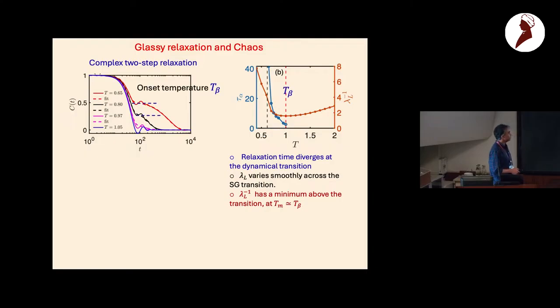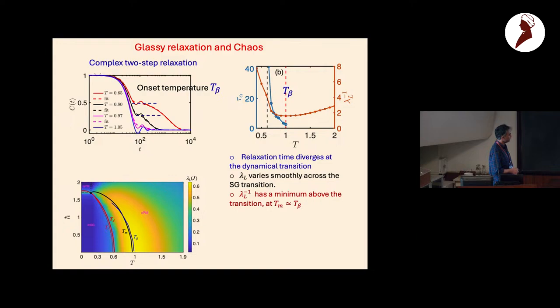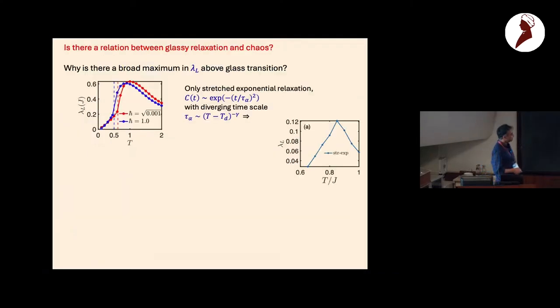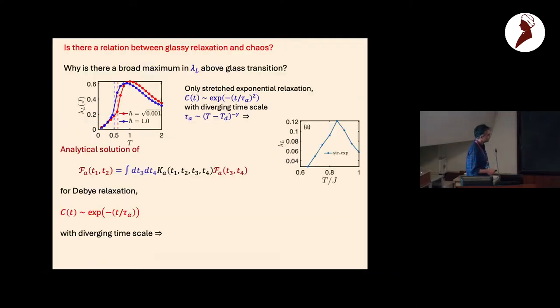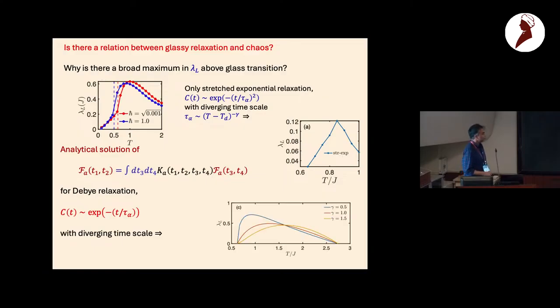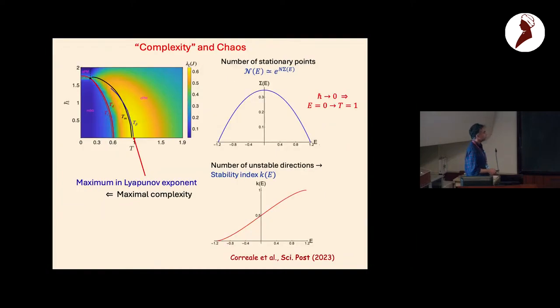So this is one thing. The second thing is that you can try to track the onset temperature, that is when this two-step relaxation sets in. If you find the onset temperature numerically, which I have plotted here as T beta, it exactly coincides with the maxima of the chaos. So it seems whenever you have this complex relaxation, the maxima is appearing, right? We have some understanding of this. In fact, we can solve this relaxation for Debye relaxation, this kernel equation, exactly, and we can show why it has this maxima and what determines this maxima. This can be done in this system.